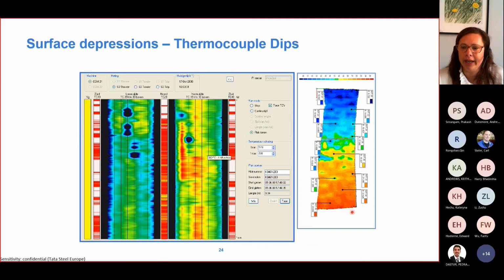If you take out a steel shell and scan it on its thickness, what you can see is that the thickness is not even. So that's really not good news, because it could have a lot of thermal stresses, but also a lot of imperfections, and it could even lead to cracking. So a test on a lab scale gives us so much information directly related to a process parameter and a process defect that is very, very valuable information for us as industrial partners.